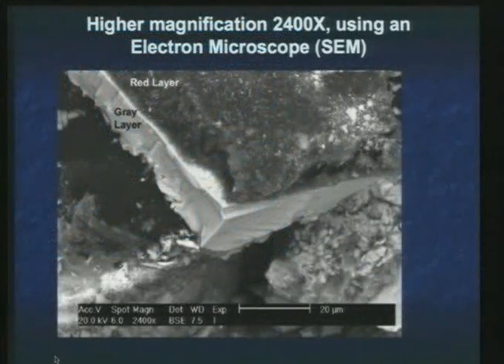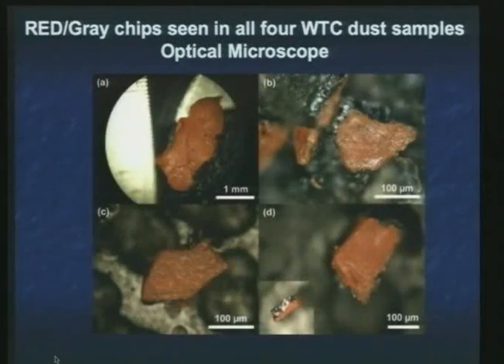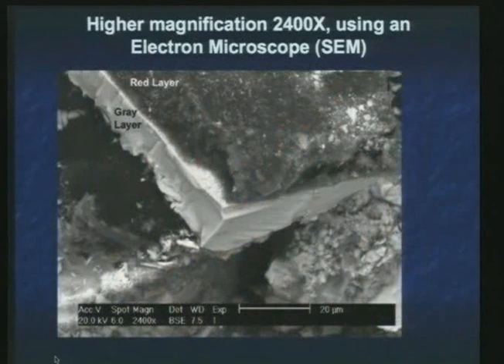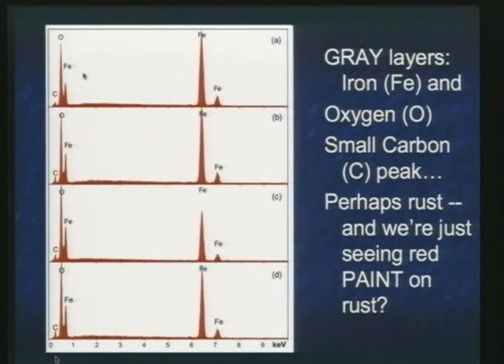This is now proceeding to a higher magnification. The previous was an optical microscope. Proceeding to higher magnification in an electron microscope, we see the red layer here on top and the gray layer below. At this magnification, we can already look at and sample the red and gray layers to get an overview of the chemicals present. We use X-ray energy dispersive spectroscopy. That will be on the quiz. Please make note of it.